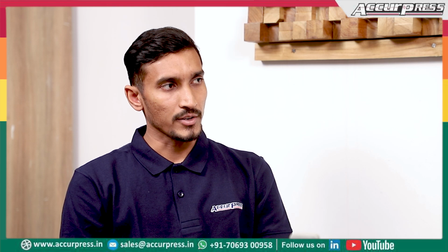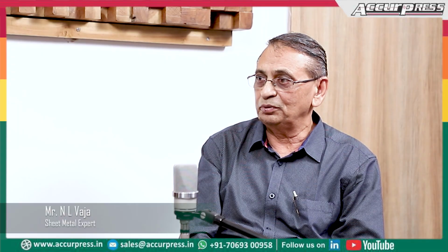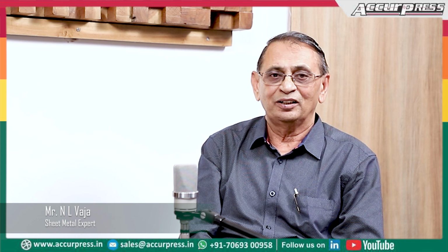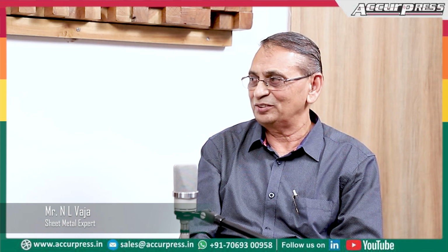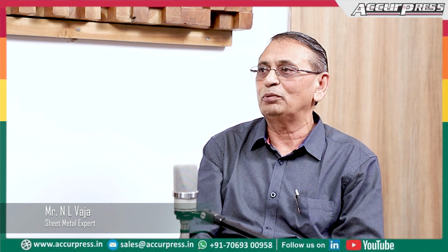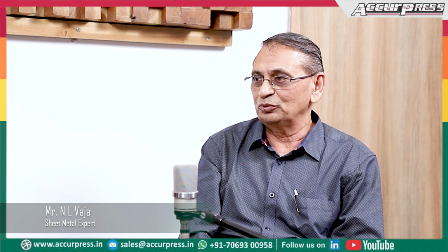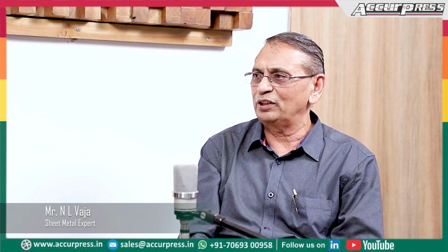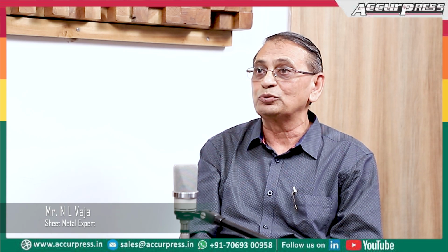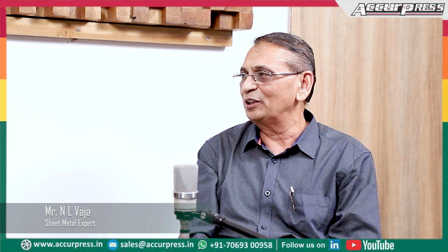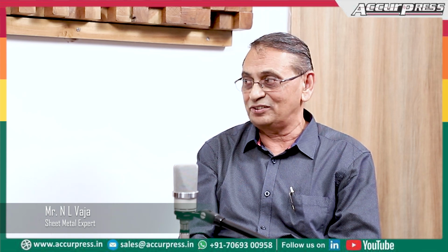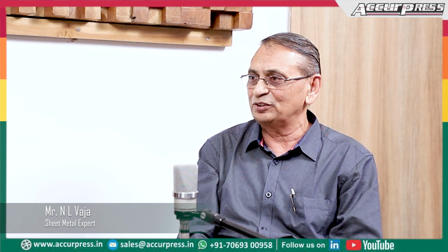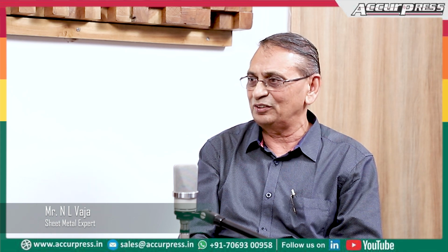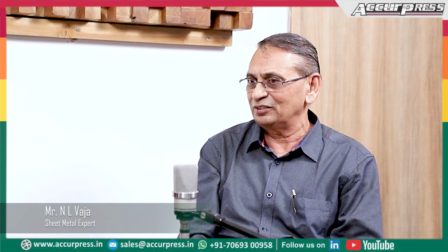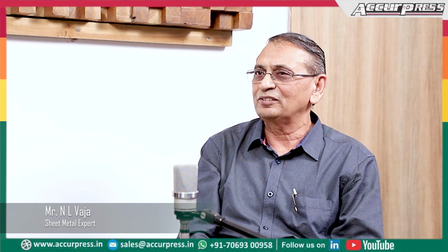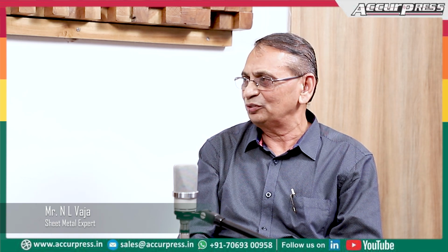Mostly, which materials are used in industries? In press industries, mostly MS, SS, a lot of material is used, but the common grade is what we call mild steel. A very common mild steel is IS 2062 grade B. It is killed by silicon, so that is why it is known as silicon killed steel. That is used in industries for making structures and all things. The carbon content in IS 2062 grade B is around 0.24, not more than that.